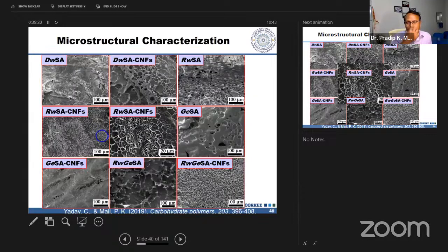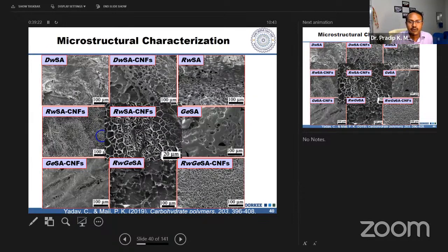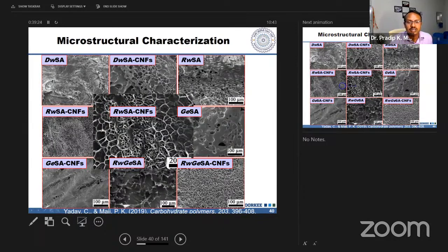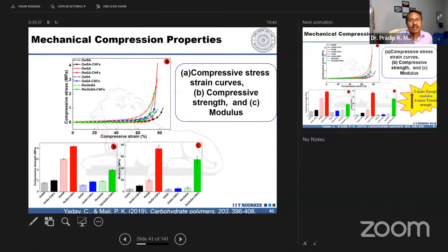Let's start from the microstructure point of view. With rice water, the sodium alginate and CNF combination is giving a very good microstructure, and because of that, stability will be very good. Now the mechanical property: compression strength with rice water, sodium alginate, and cellulose nanofiber shows a very good increment of the compressive strength. The modulus value is also very, very good.